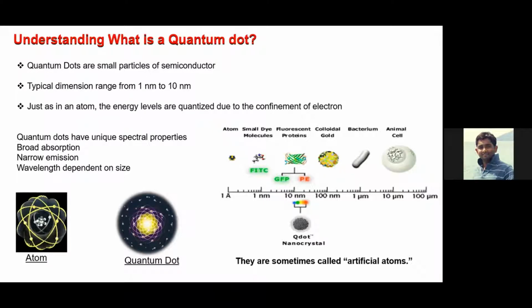But metals, semi-metals, and other things we can make, but not so easily. In general, quantum dots are made from semiconductors, and the typical dimension is 1 to 10 nanometers. I say typical dimensions because different semiconductors have different band gaps. For example, if you take cadmium selenide, the bulk band gap belongs to the red part of your visible spectrum. So the maximum size you can go to is 7 to 8 nanometers.